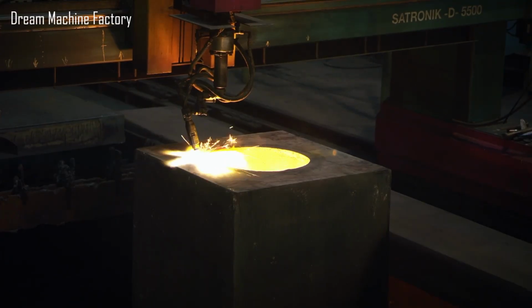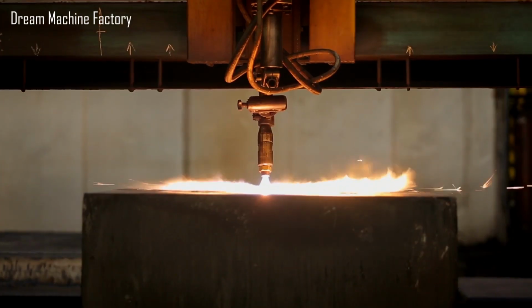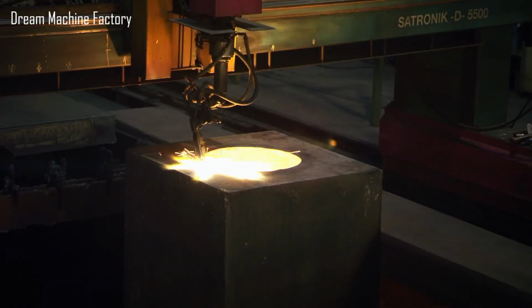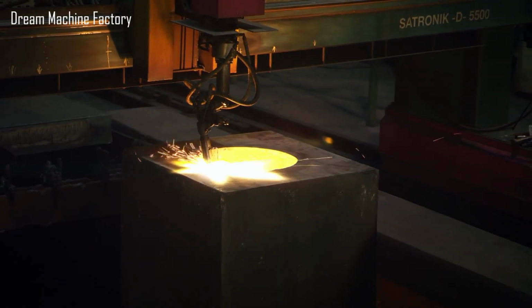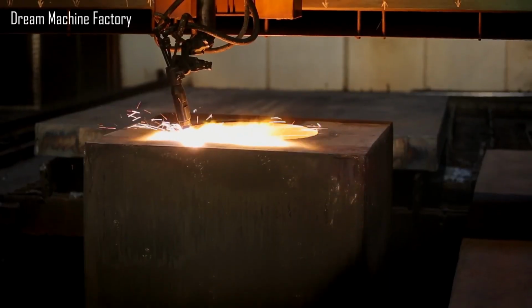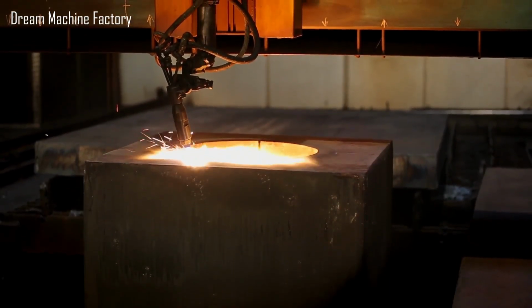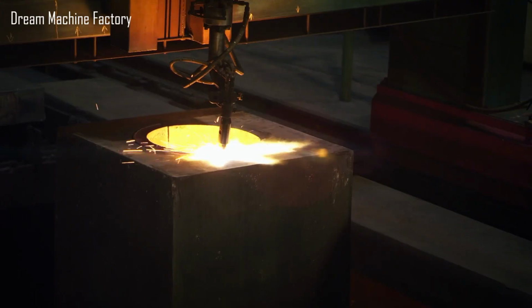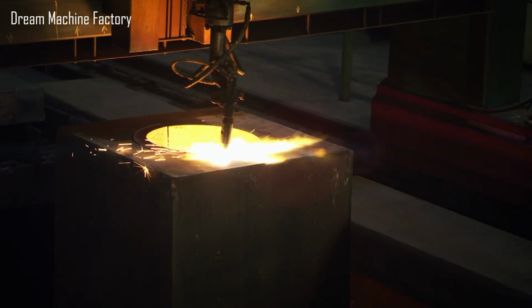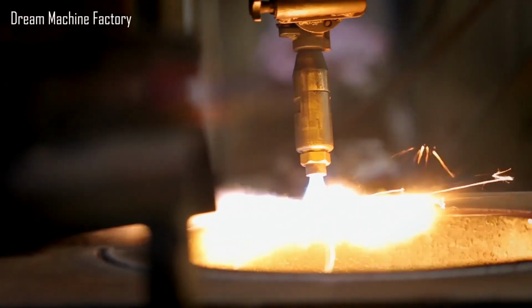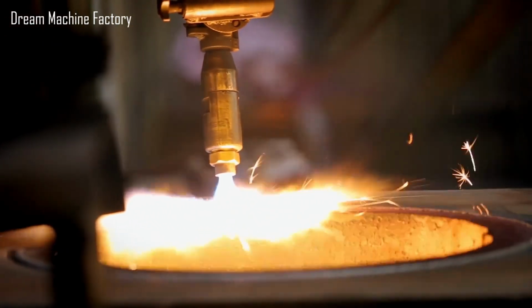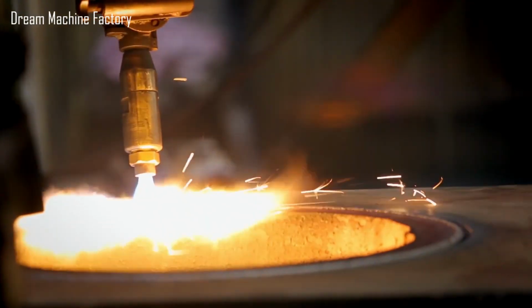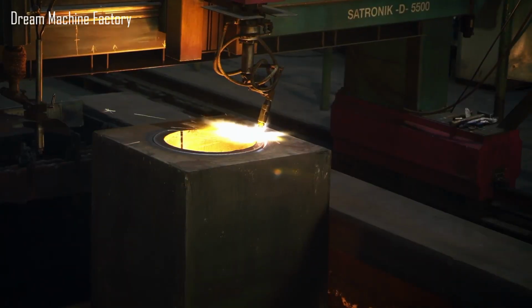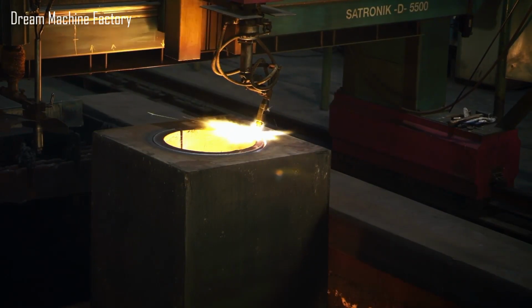As with previous cuts, the steel was first heated to ignition temperature using a high-temperature flame. Then, a focused stream of oxygen oxidized and removed the molten material layer by layer. Special attention was paid to maintaining a smooth taper and even surface throughout the cut. This stage demonstrated the capability of oxy-fuel technology to perform not only straight cuts, but also complex geometrical shapes in thick steel sections with high precision.